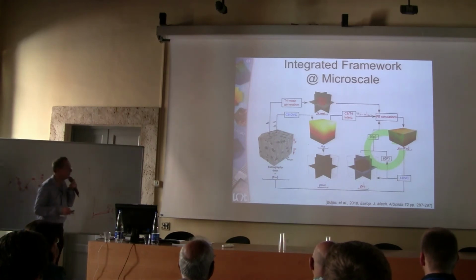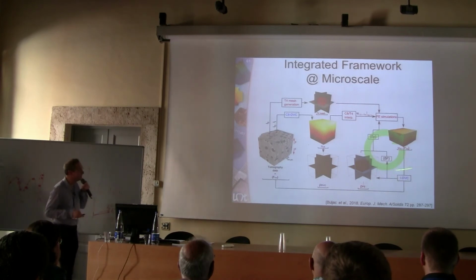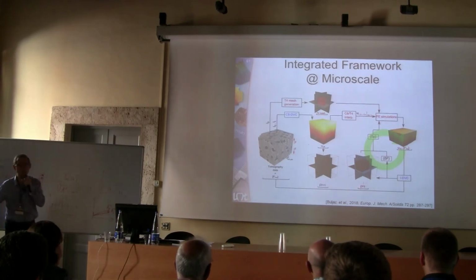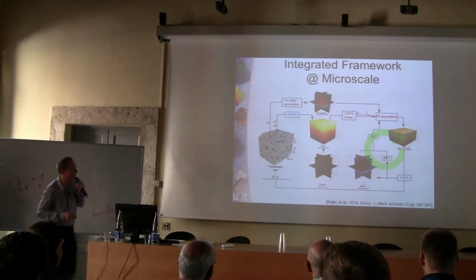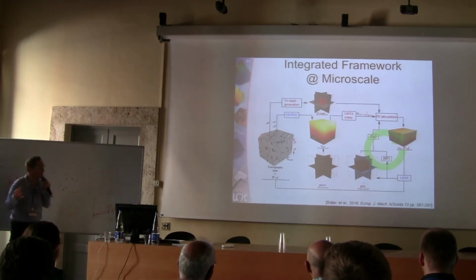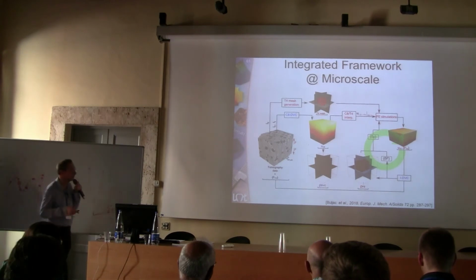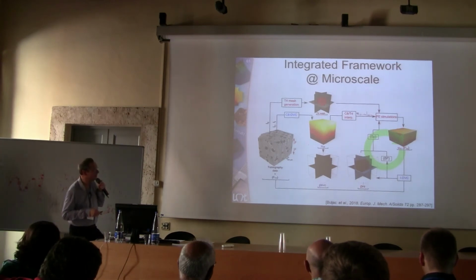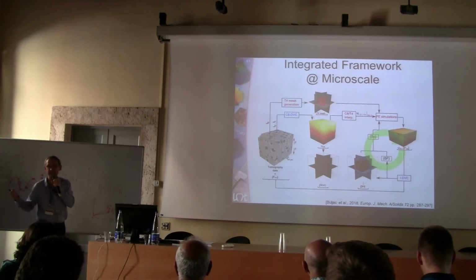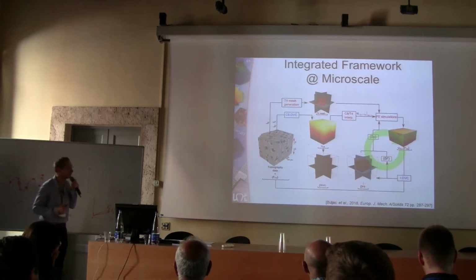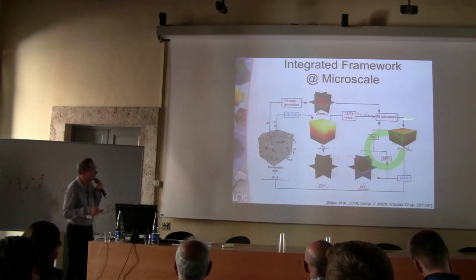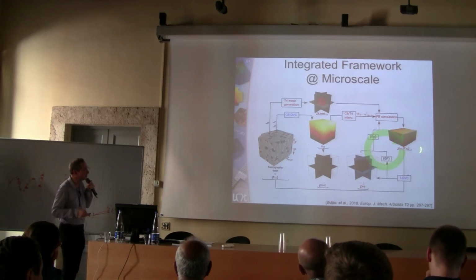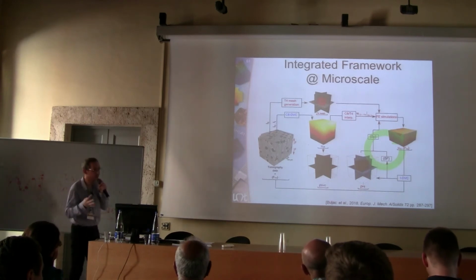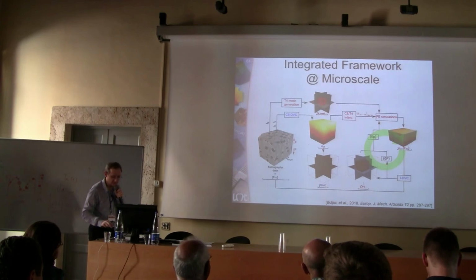Indeed, it's possible, and in this particular case it was performed via what we call integrated DVC, namely the fact that the gray level residuals are still considered in the registration scheme, which now explicitly depends on your material parameters. In this setting, you determine directly the material parameters in such schemes.